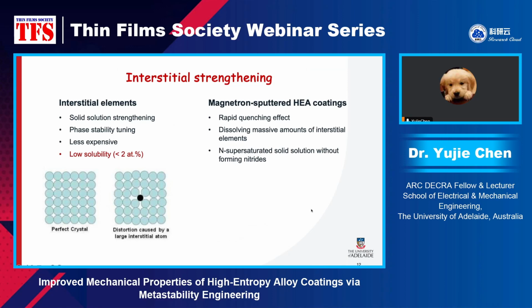If you're working on thin films and coatings, you should be quite familiar with magnetron sputtering. It is a physical vapor deposition technique used for depositing high quality coatings. It's a bottom-up approach, so the rapid quenching effect is very important. It deposits the coating layer by layer, atomic layer. So the cooling rate is super fast. The high cooling rate will suppress the diffusion.